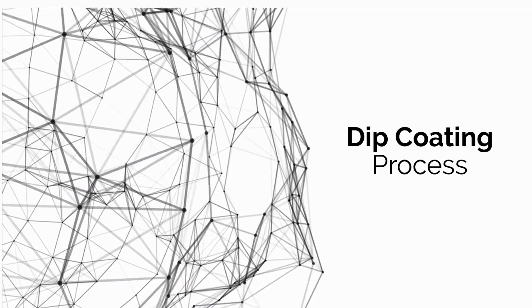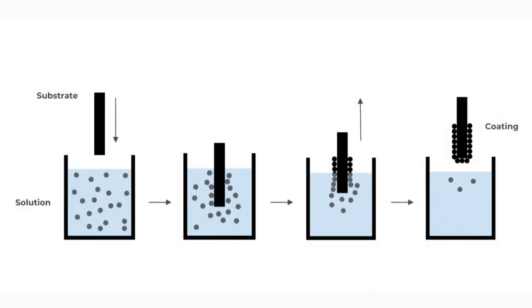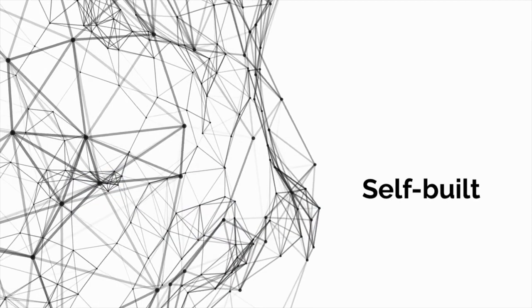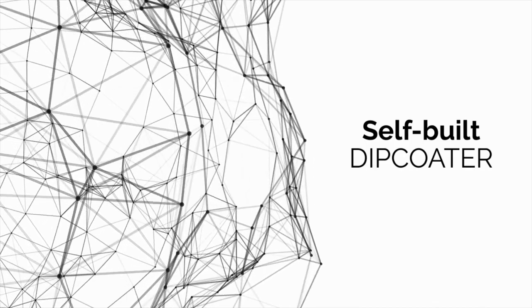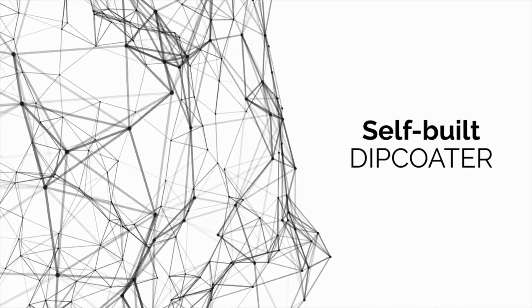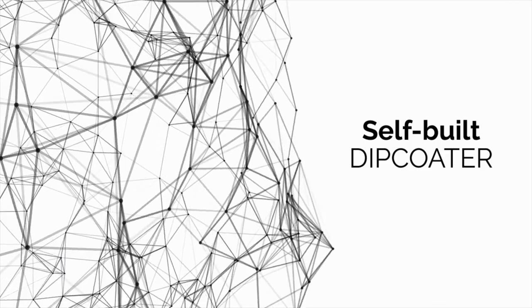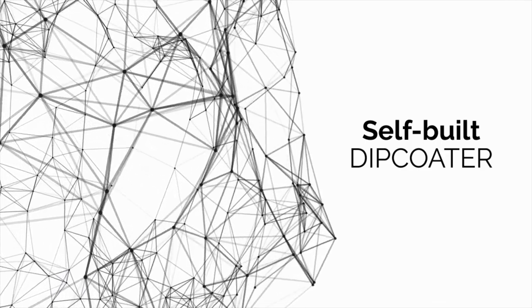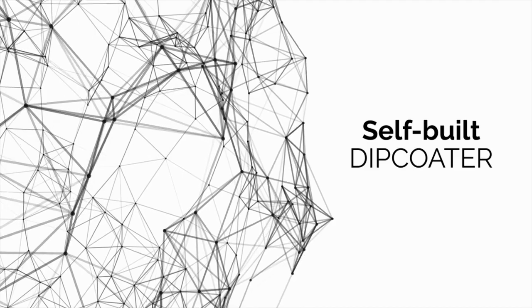In order to make the quantum dots into a thin film, we use a technique named dip coating, a process by which substrate material is submerged in conformal coating, then taken out and allowed to drip dry. Because commercial dip coaters cost more than $3,000, we decided to fabricate our own dip coater from scratch. Here's a video of the dip coater we built that cost only $350.